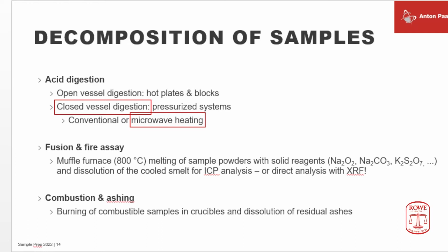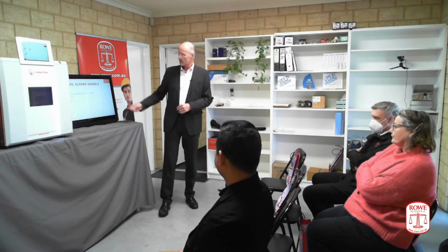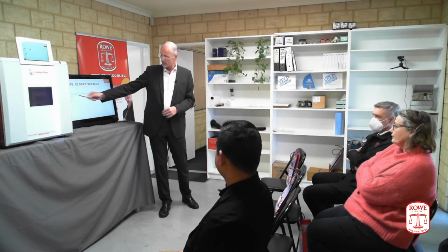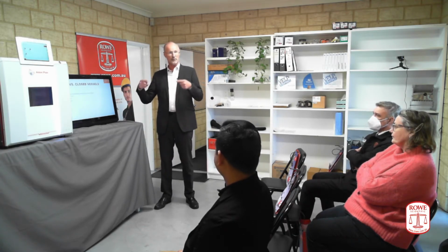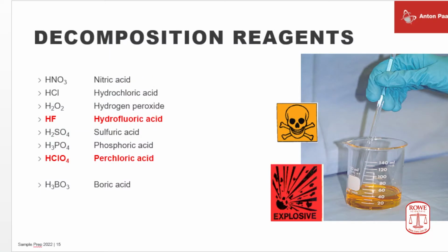When we talk about digestion, it's a question, do we do it in open vessels, beakers, hot plates, or do we do it in closed vessels? The limitation of open vessel digests is mainly the boiling point of the reagents. So if you do it with nitric, you are limited at 122. Of course, you could add some sulfuric to the mixture to increase the boiling point. On the other hand, sulfuric acid is disadvantageous for the ICP analysis. So keep the chemistry simple, use as few acids as needed to completely digest the sample, and try to take the acids to higher temperatures.